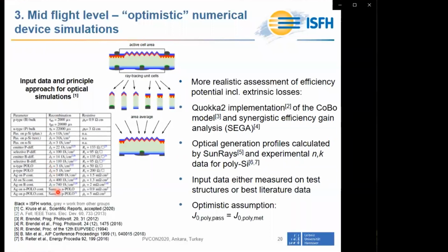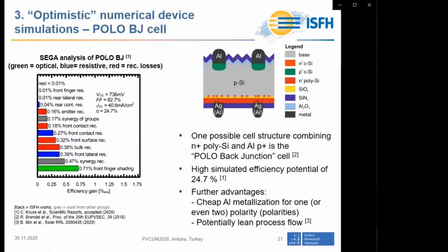It's probably difficult to read them now, but I would like to refer you here to our recent publication. Briefly summarized, these input data are either measured on test structures or best literature data. So these are the best data for each quantity we can achieve or found in the literature. We also make the assumption that the polysilicon can be metallized without harming its passivation quality, which is at least more or less true for n-type doped polysilicon. One possible cell structure comprising this combination of an electron collecting N+ POLO junction with the hole collecting aluminum P+ regions is this POLO back junction cell as shown here.